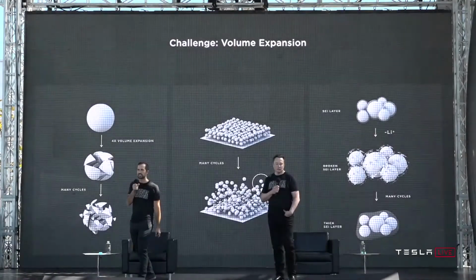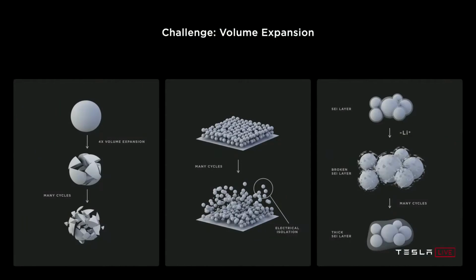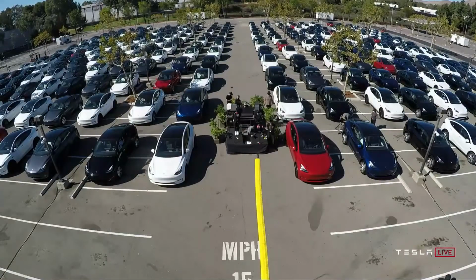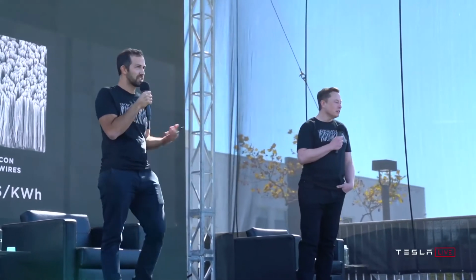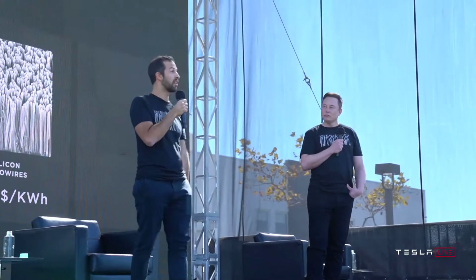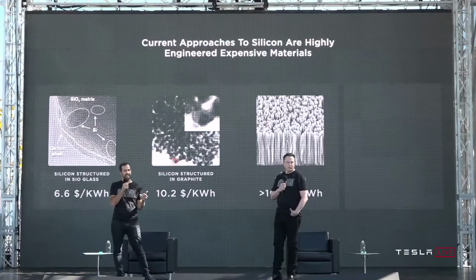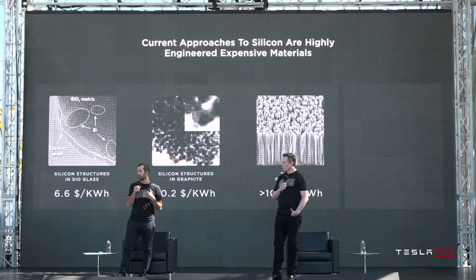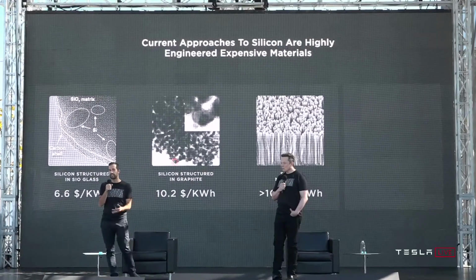The main reason is that silicon expands 4x when fully charged with lithium. All of that expansion stress makes the particles start cracking and electrically isolating, you lose capacity, the energy retention of the battery starts to fade, and it also gums up with a passivation layer that has to keep reforming as the particles expand. Basically, with silicon, the cookie crumbles and gets gooey. Good analogy. And current approaches to solve this, which exist, I mean, we have silicon in the cars that you're all in right now, involve highly engineered, expensive materials in the scheme of things. Now, they're still great, and they enable some of the benefits of silicon.